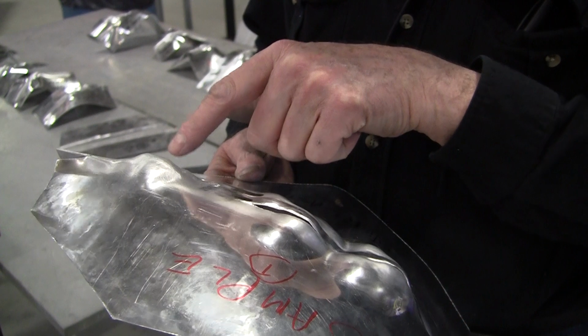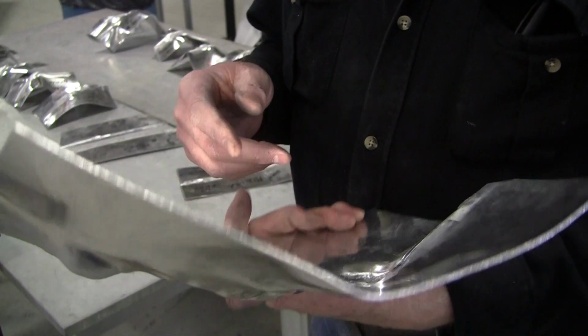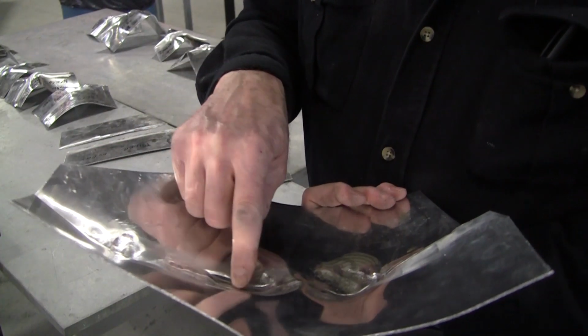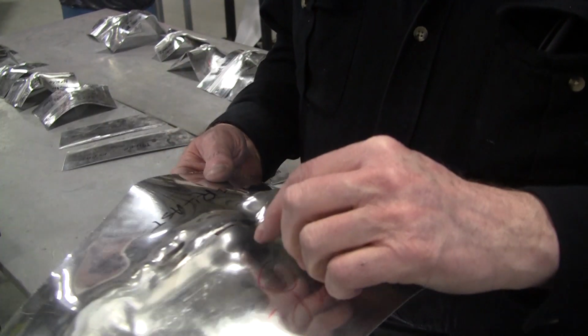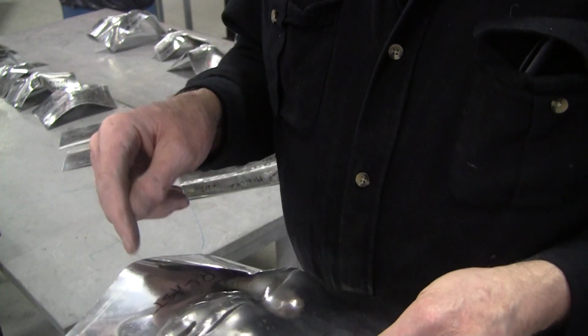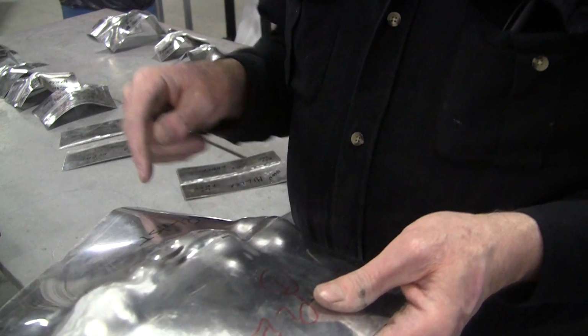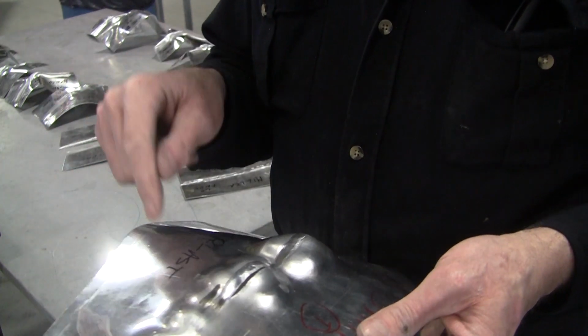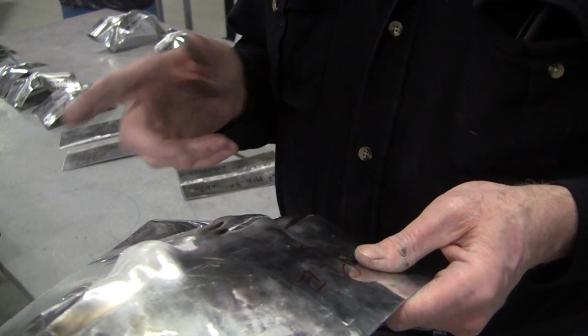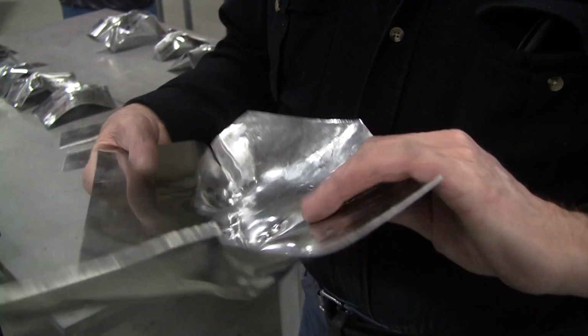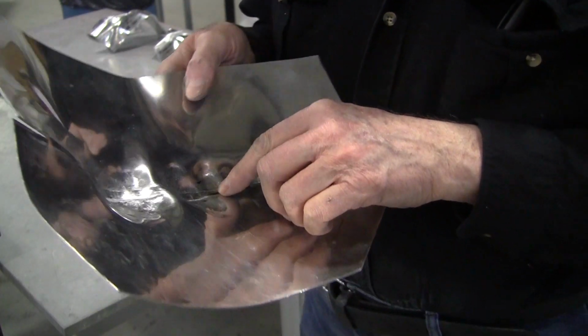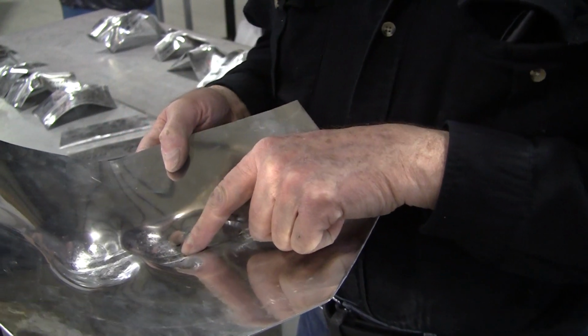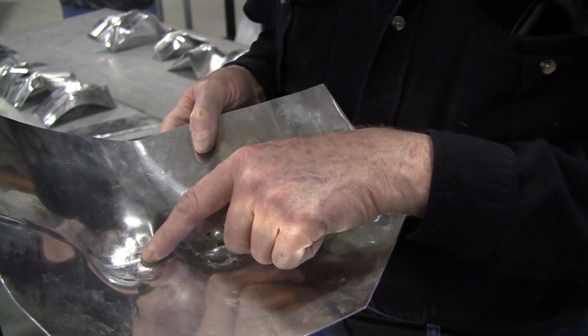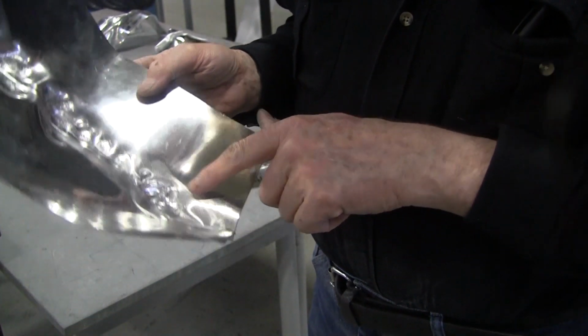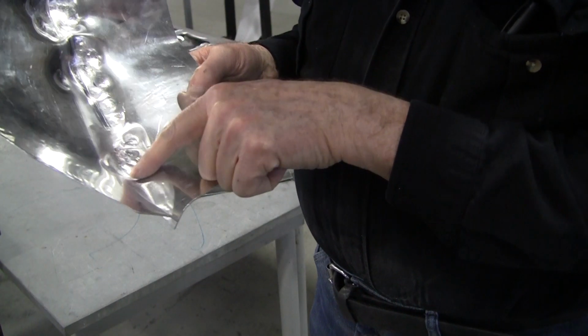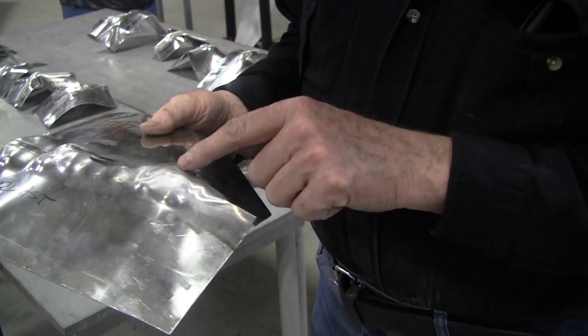So that's proof that my theory was correct, that it was those little undercuts on either side of the weld that really broke, because when you take aluminum and you scratch it and you bend it, it'll break right where you scratched it. So that was a stress fracture point. So this wasn't a failure of the weld, it was a failure of my technique in grinding. And then I did the grinding properly on this little end over here, and it passed the test perfectly.